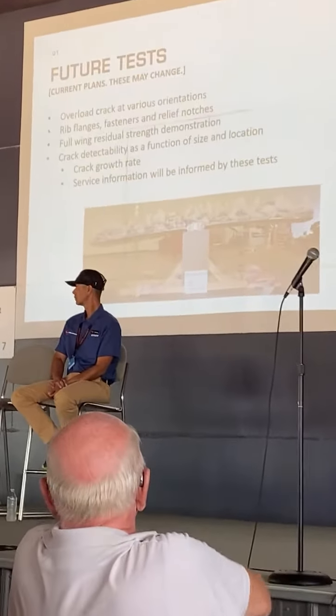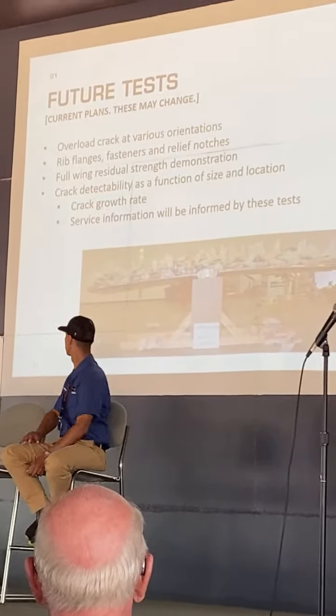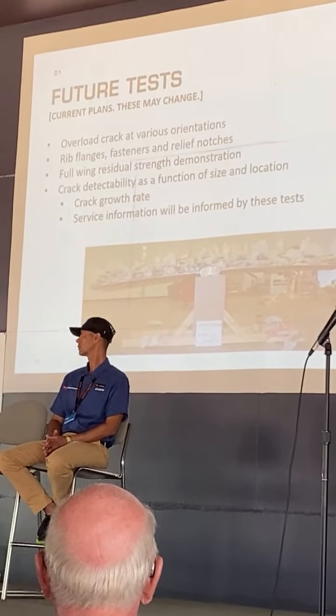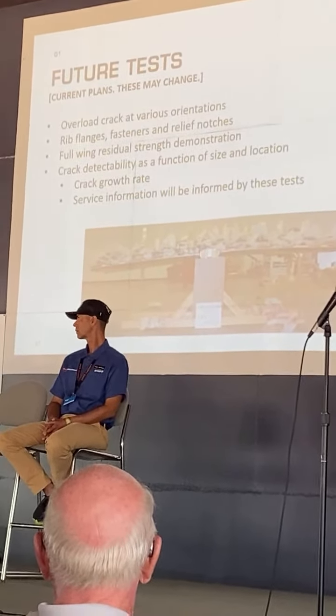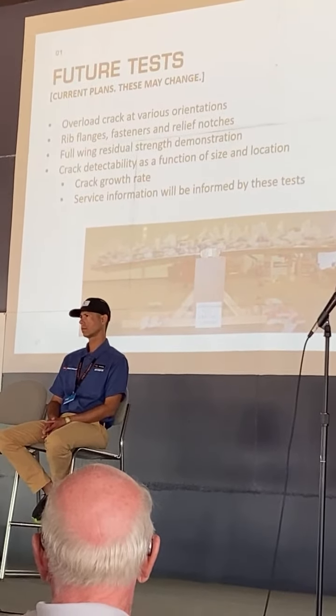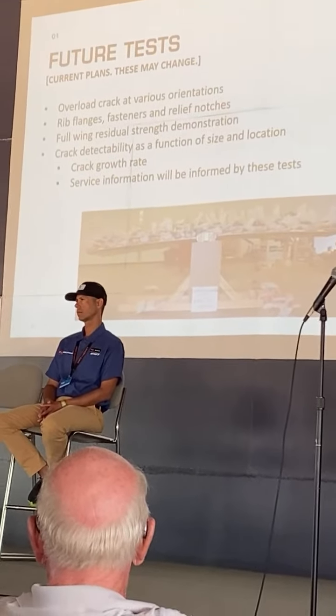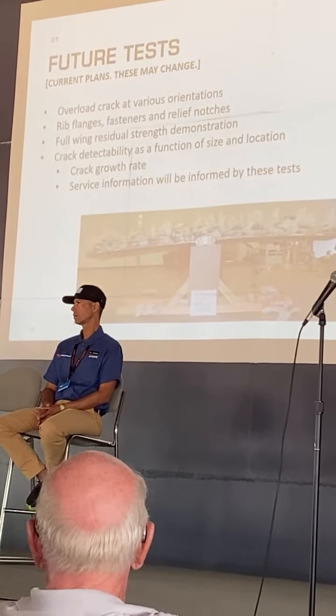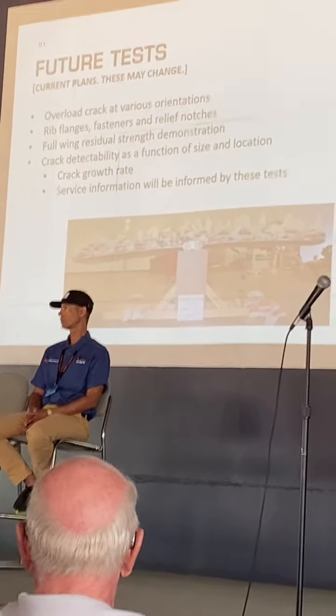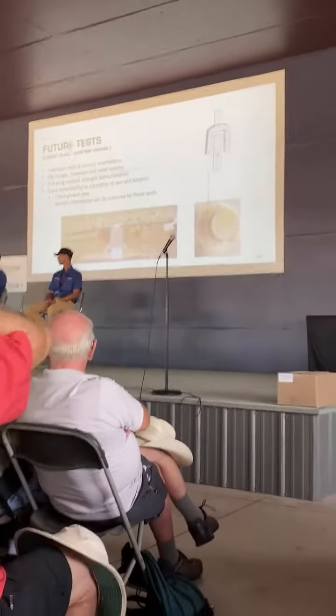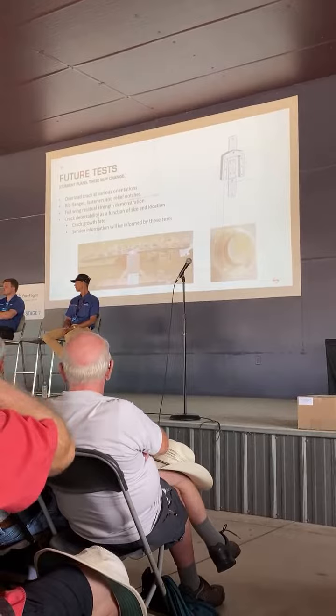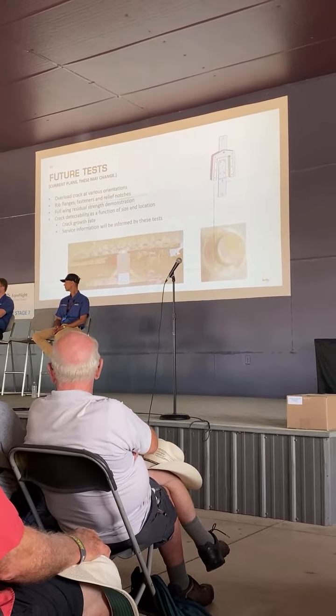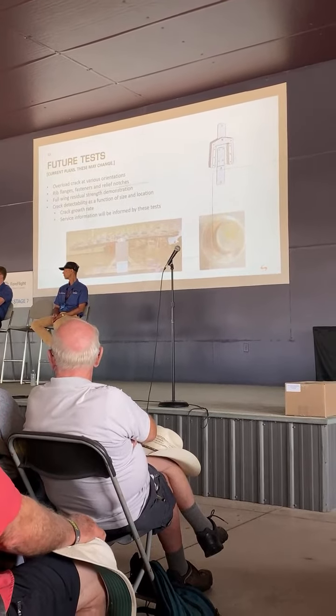So the future tests that I've already alluded to that we're currently conducting, and there will be more tests. Again, we've sat down with our third-party consultants and asked what could the worst case scenarios be, make a list, take the top 3, test those, and then come back to the problem after we learn and determine what tests we're going to do next. What tests are valid and will get us the best information most quickly. Overload the crack at various orientations. So as I explained, we're moving the failure point around the crack, its orientation, and other variables are being varied as well. The rib flanges, test coupon that you can see on the upper right there. So testing notches and the rib flange itself, where we can vary the shear force and the pull force.